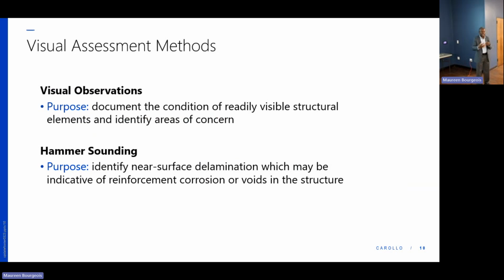or if there's a void behind it, maybe indicating that some corrosion is taking place behind what you can see, or perhaps during the pour process, there was a void there due to maybe segregation of the aggregates because they were not compacted well enough. And so there's a hole behind it. And so that hammer sounding is important to do that. It helps us identify areas of corrosion and then voiding in the structure as noted.